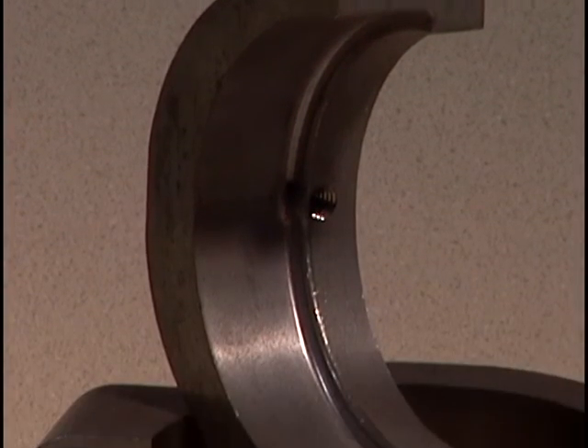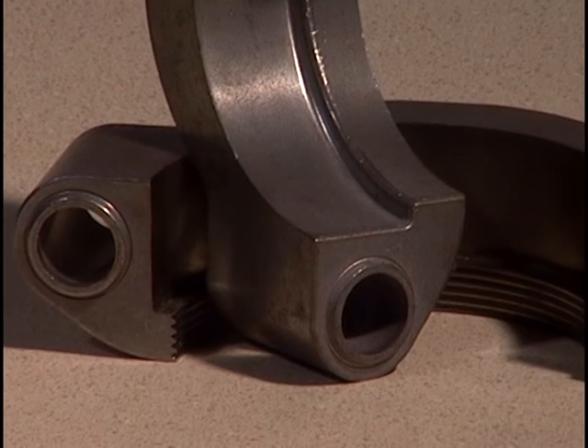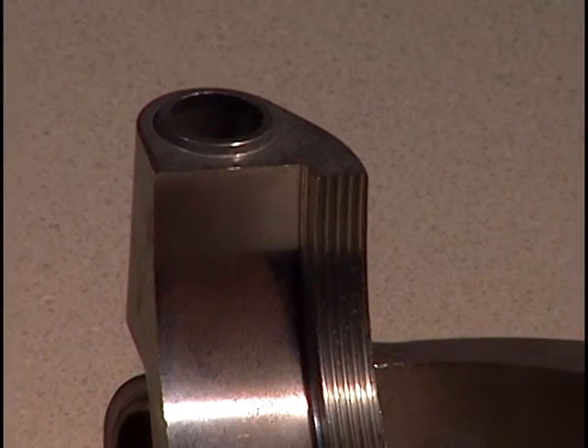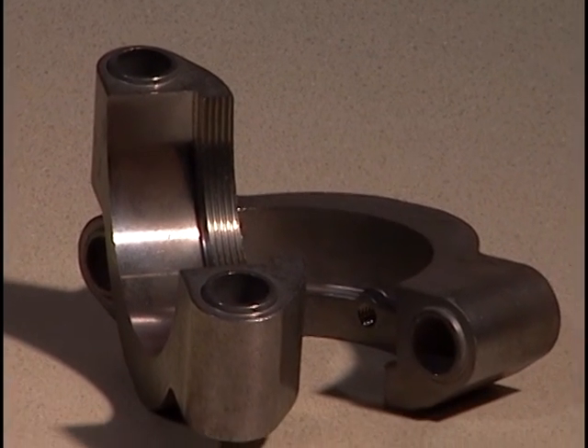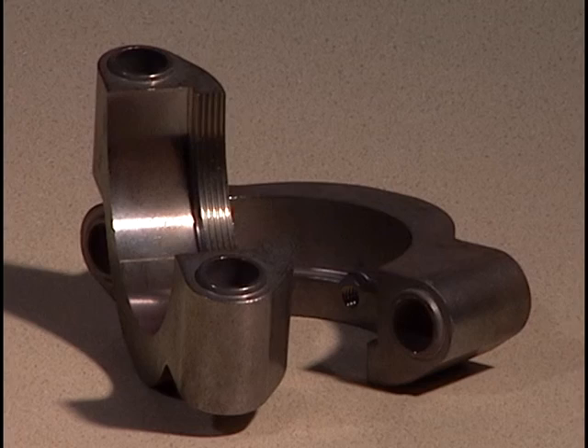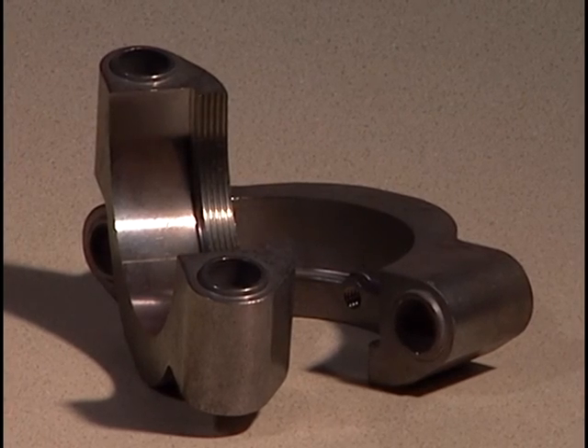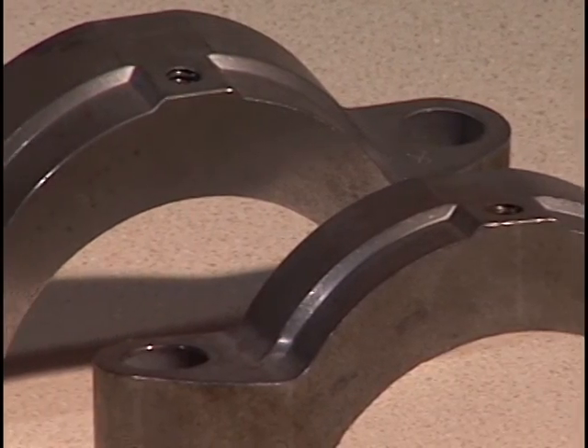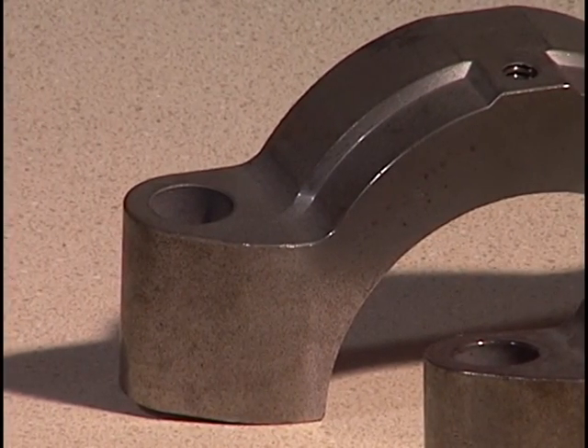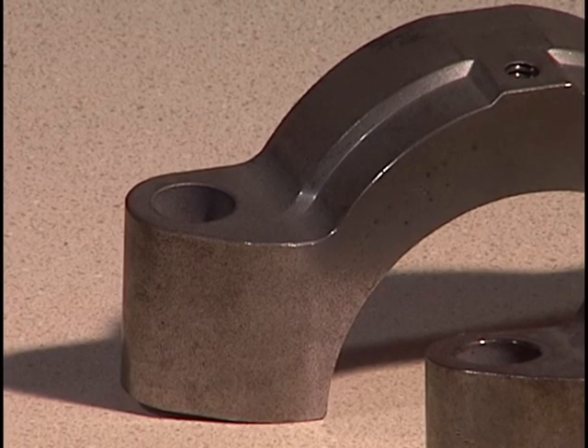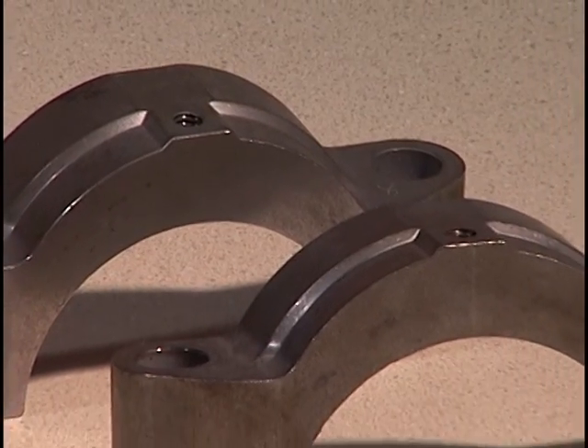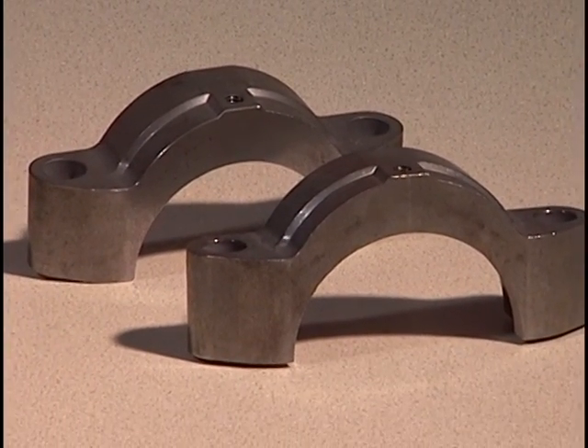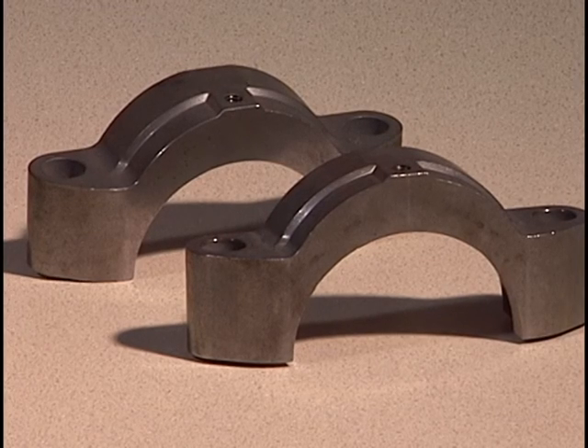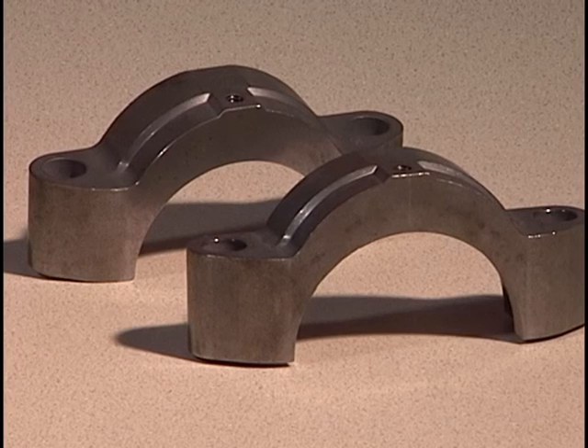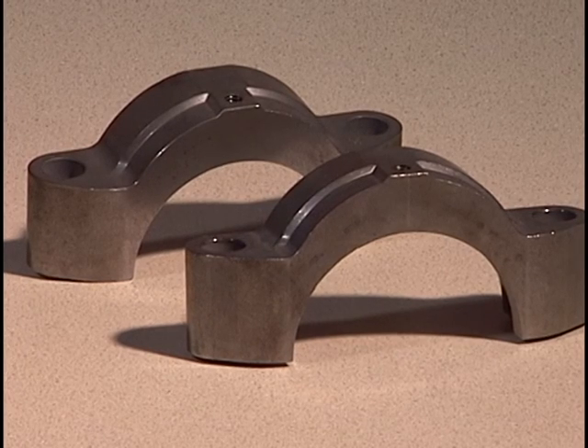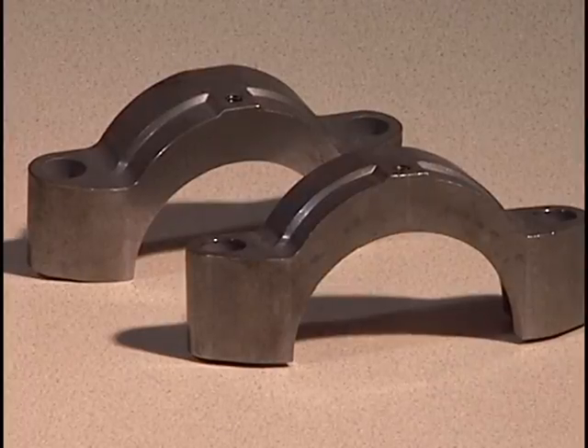Made from a specially designed machinable material, the part is assembled with a cast iron housing and simultaneously bimetal machined with an inside diameter bore and threading. The new PM design eliminated 5 secondary operations previously required on the casting. The part is made to a minimum density of 6.6 grams per cubic centimeter in the arch. It has an ultimate tensile strength of 70,000 psi, an elongation of 3%, a fatigue endurance limit of 26,000 psi, and a 75 HRB apparent hardness. Annual production could top 1.8 million parts.